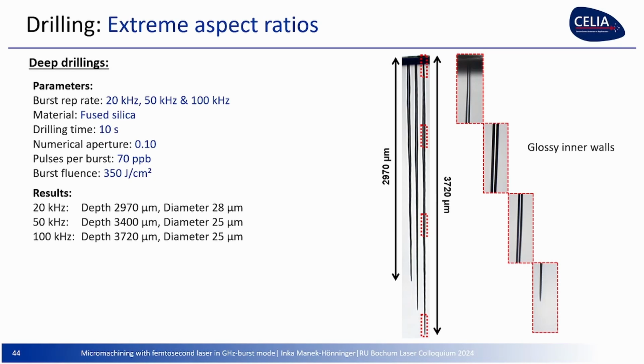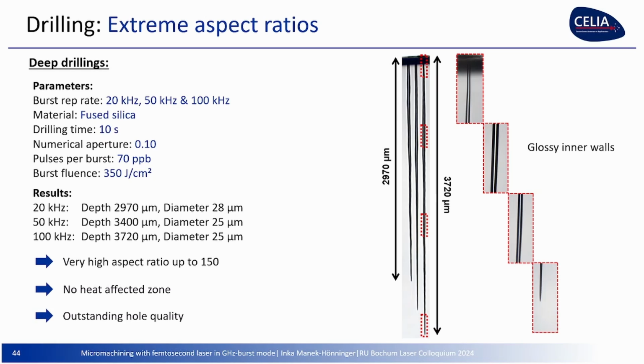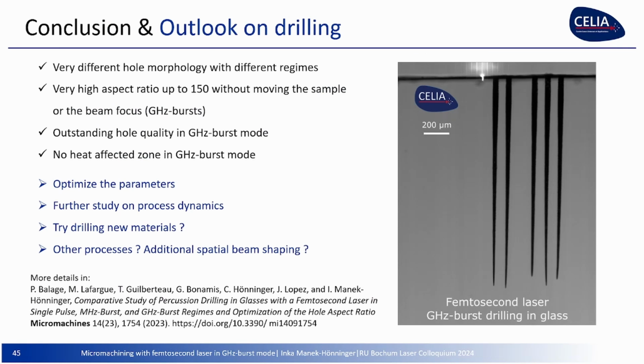So all along the hole, the walls are very glossy. So it is possible to get aspect ratios up to 150 with this drilling method, with no heat affected zone, at least in the silica. So let me summarize on drilling.